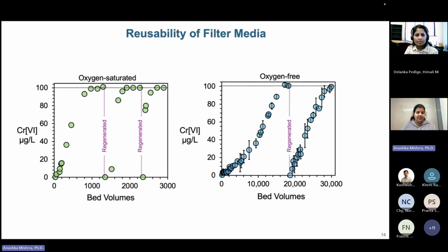But for the oxygen-free condition, when we clean the filter and run it again, it can still go for another 10,000 bed volumes, which is again promising because it expands the lifetime from 17,000 to about 27,000 bed volumes of treatment.